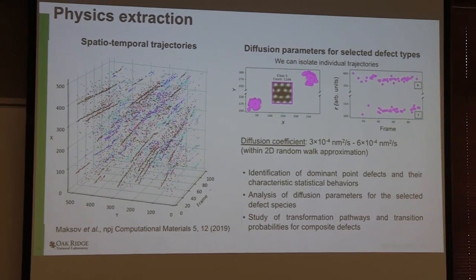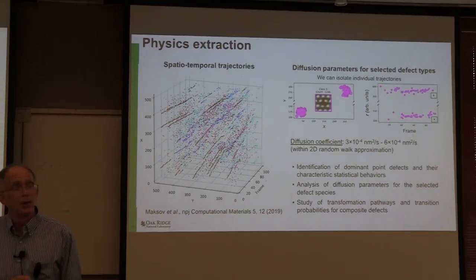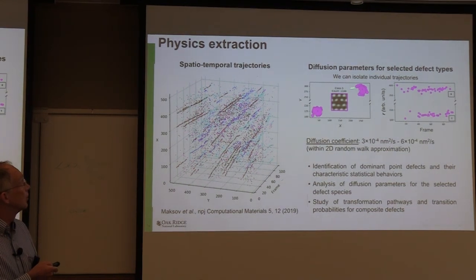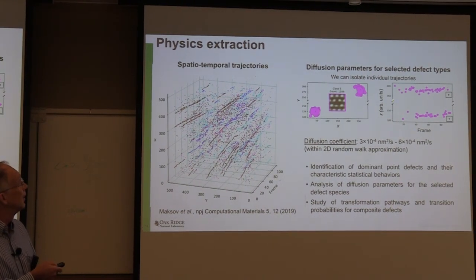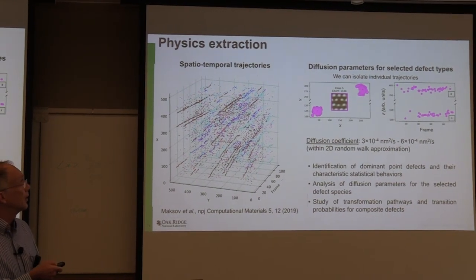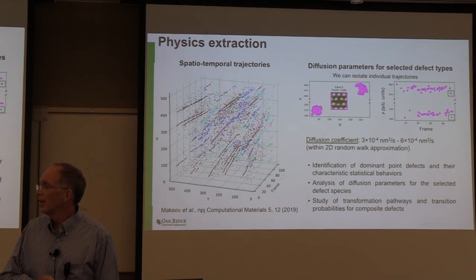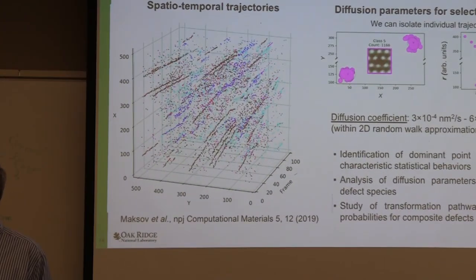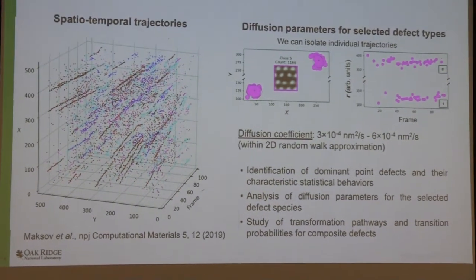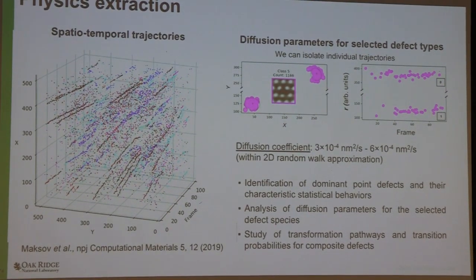Like I mentioned, the sulfur vacancy is one of the biggest ones. And you can cluster those into 2 different types of trajectories. And then you can plot out the trajectory over time and get the diffusion coefficient. And that works quite well. And if you do a Monte Carlo model of this, you get the same diffusion coefficient. And I didn't do any modeling here.